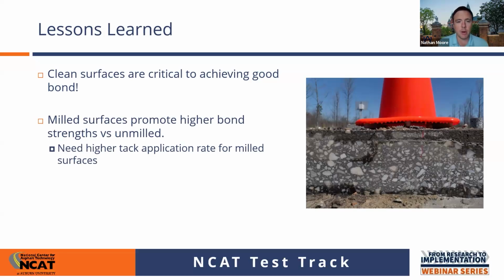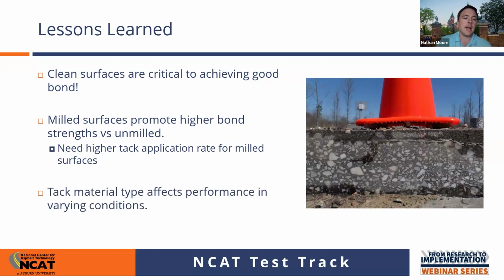Milled surfaces will promote higher bond strength than unmilled. Sometimes you may not be doing a mill and inlay, and so you don't necessarily have the option. But historically, milled surfaces do provide higher bond, because not only do you have the bond from the material, but you've got mechanical interlock between the materials and the two layers. And tack material matters, and it affects performance in varying conditions and over time.